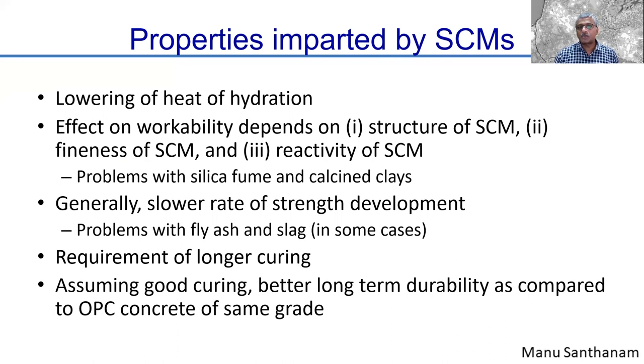Strength development is generally slower because obviously the pozzolanic materials or supplementary materials need this calcium hydroxide that is getting generated. So it takes a while for them to really get going. As a result, you may have to sometimes do a longer curing, especially when you have fly ash or slag. If you have calcined clays, you probably don't need to do that because the reaction is relatively faster. And if you do this good curing, you generally expect that the durability of concrete produced with supplementary materials is going to be significantly better than with ordinary Portland cement concrete.